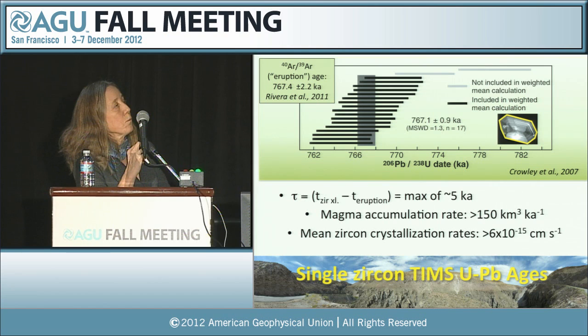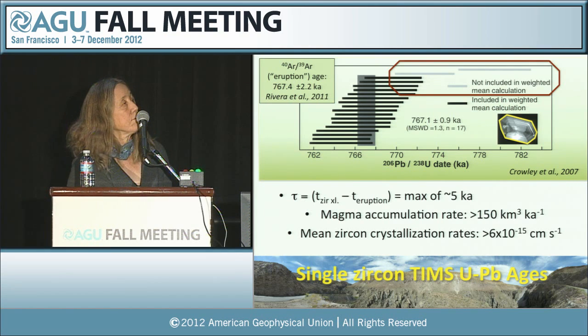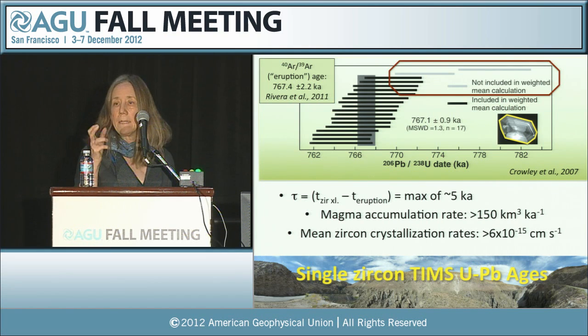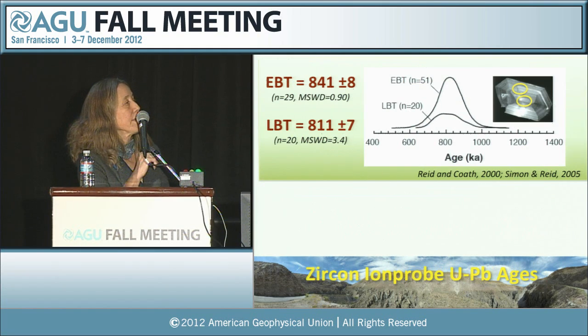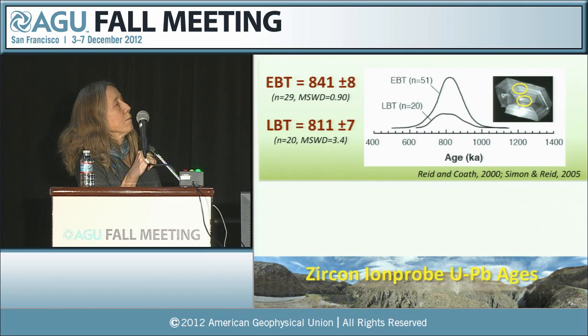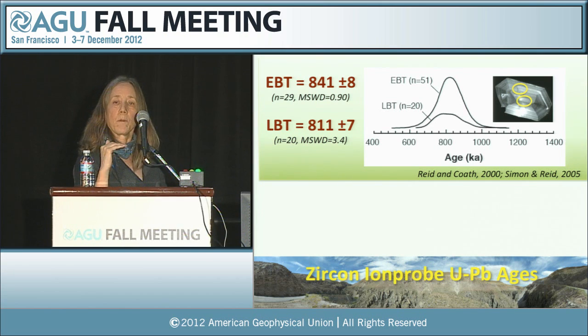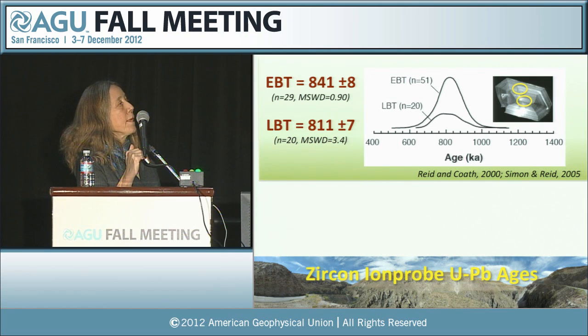Now, I want to point out the fact there were a couple of outliers here that they excluded from this mean crystallization age. So there is a hint that there might be something older in these zircon populations. And in fact, I had looked previously at this, as has Justin Simon, in two studies that we had done on the Bishop Tuff, where instead of looking at a whole zircon, we'd done spot analyses on cross sections that were exposed within the zircon crystals. And what we found was some difference between the earlier erupted part of the Bishop Tuff and the later erupted part of the Bishop Tuff.